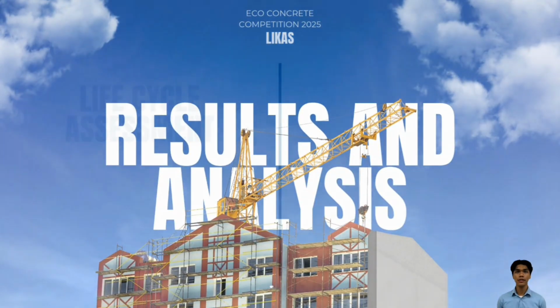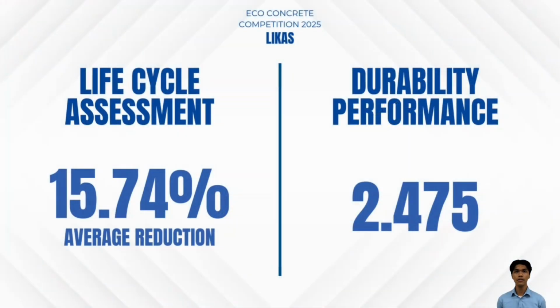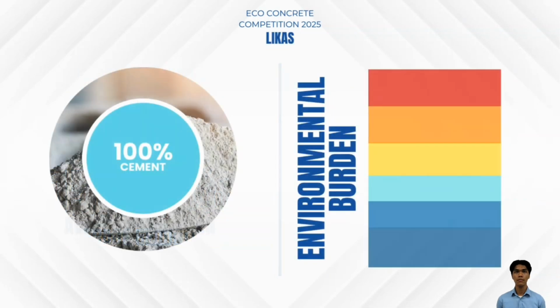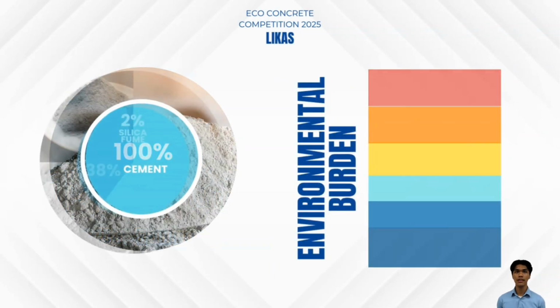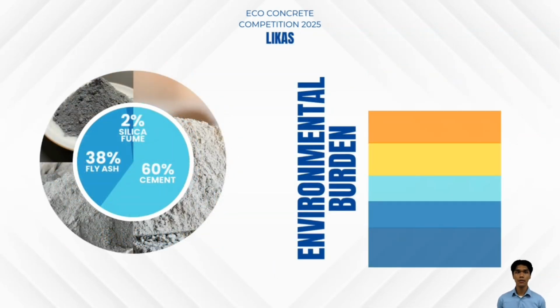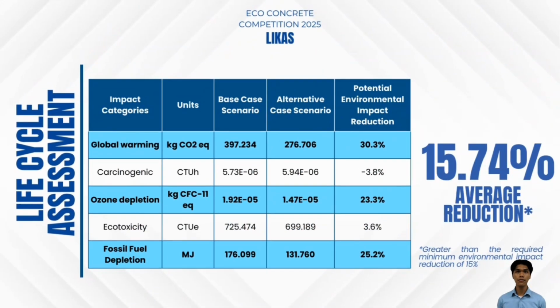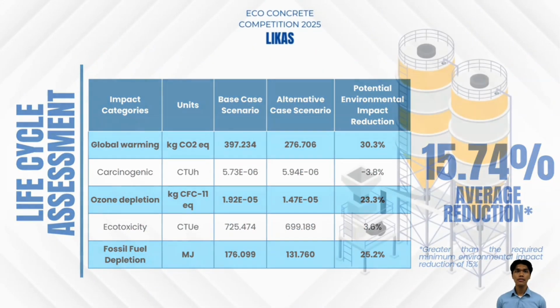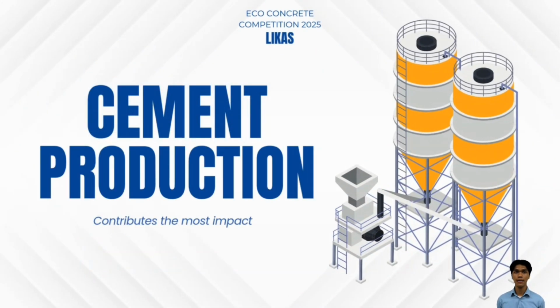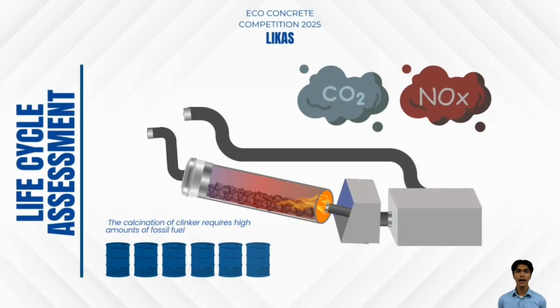The use of SCMs as a partial replacement for cement results in a significant reduction of environmental burdens in concrete mixtures, with an overall reduction of 15.74%. The greatest reductions are observed in global warming, followed by fossil fuel depletion and ozone depletion. Cement production is the primary contributor to these impacts. The calcination of clinker requires high amounts of fossil fuel, and the combustion of this material releases substantial carbon dioxide emissions, contributing to global warming, and nitrogen oxides, a major cause of ozone layer depletion.